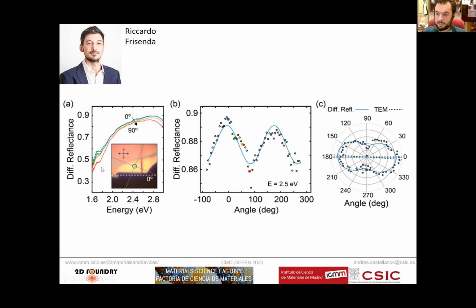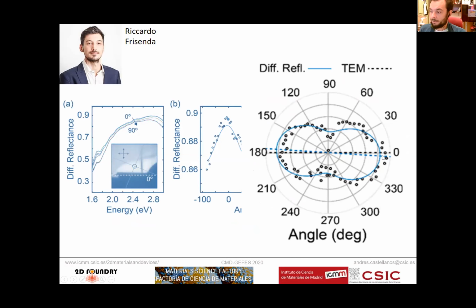optical and electrical anisotropy. For example, here you can see differential reflectance spectra taken with light that is linearly polarized, and we start rotating the polarization of the light. And what we see is that the differential reflectance has a maxima and a minima at certain positions. So we can see a polar plot here, and basically in this polar plot the maximum position of the differential reflectance, which corresponds to the maximum optical absorption of the system, is almost perfectly aligned with the direction of these ripples that we see in the TEM. This little difference here is within the experimental resolution that we have in the alignment between the two images.